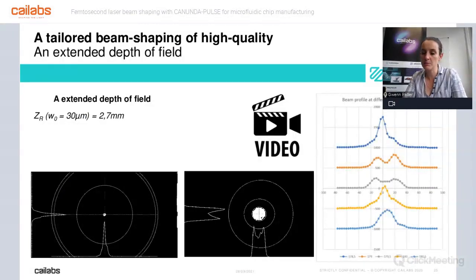When you want to have also a high quality beam shaping, there is something else which is very important, is phase management. So most of the time, having a nice top hat, a nice shape is possible also in one single plane, but what is very difficult is to preserve it over a certain depth of field. So the reference generally is the Rayleigh range, so ZR, and we will compare it to the Rayleigh range of a Gaussian beam, the equivalent size Gaussian beam, and the Rayleigh range of a 30 micron waist Gaussian beam is 2.7 millimeter. And what you can see here is that we managed to preserve this U shape over 1 to 2 millimeter, enabling to have a pretty robust process. So you can see on the left the image when you are far from the best focus plane, and the image of the U shape in the focus plane and how it's behaving through the propagation distance.